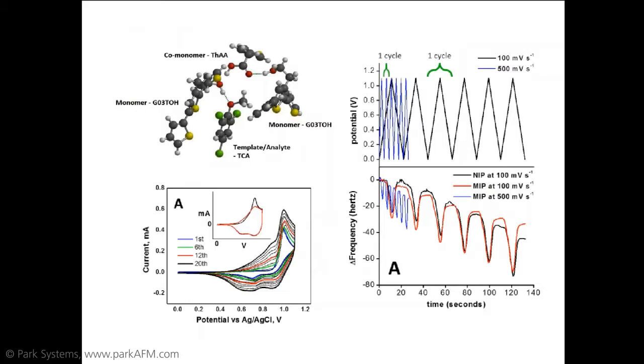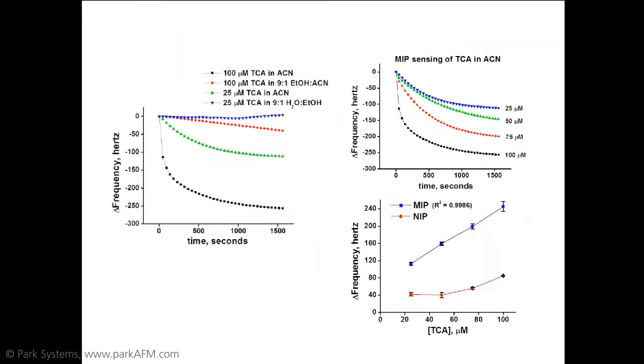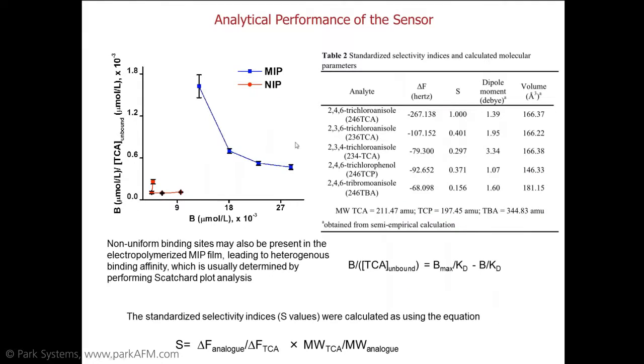And again, we employ the same tools. We did the modeling. In this case, we actually used a co-monomer modeled with the template molecule TCA. We optimized the deposition by looking at the cyclic voltammogram as well as the quartz crystal microbalance trace. What we demonstrated is that you have high sensitivity and selectivity, including the optimized films between the molecularly imprinted and the non-imprinted polymer. And here you can see that the MIP has good binding characteristics compared to the NIP. And so the performance of the sensor again was validated by these sensitivity and selectivity techniques.